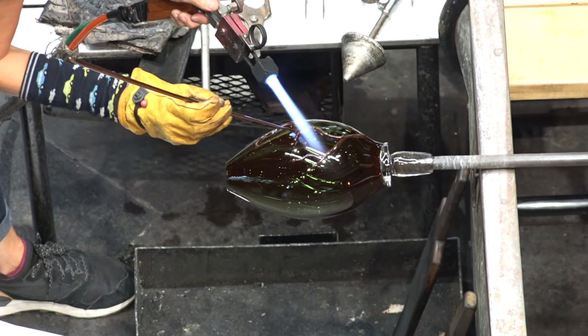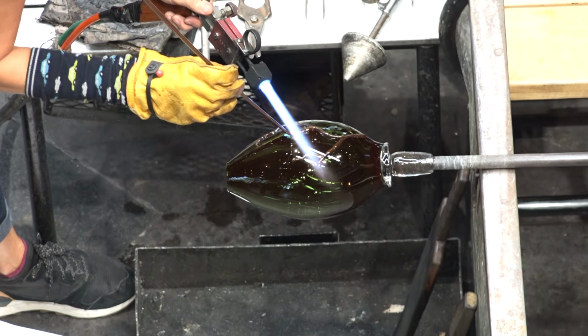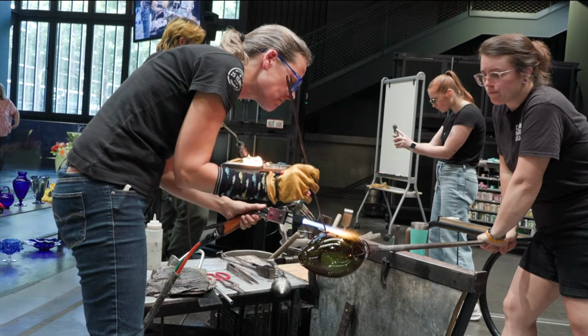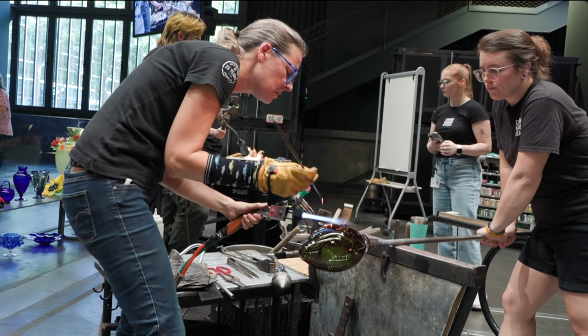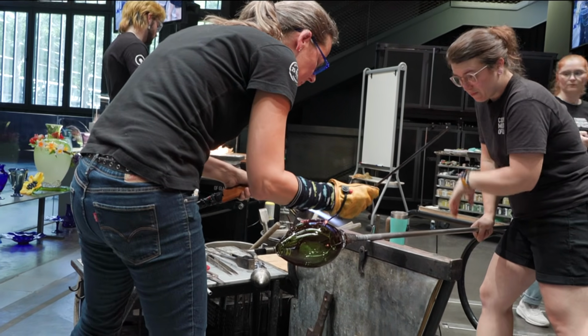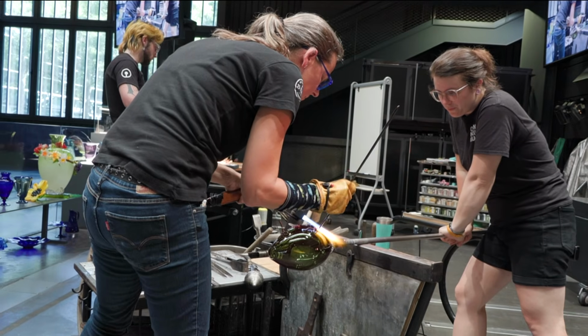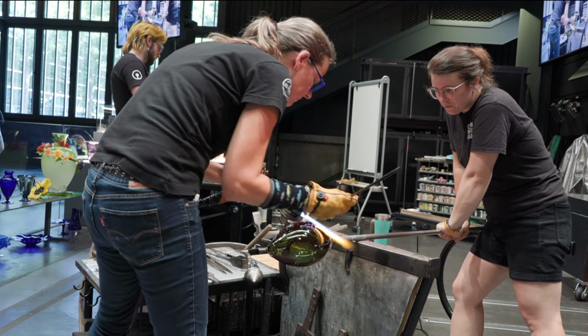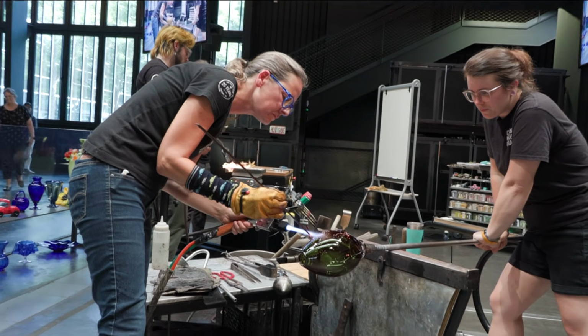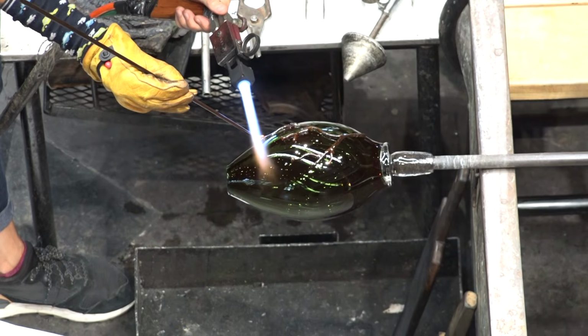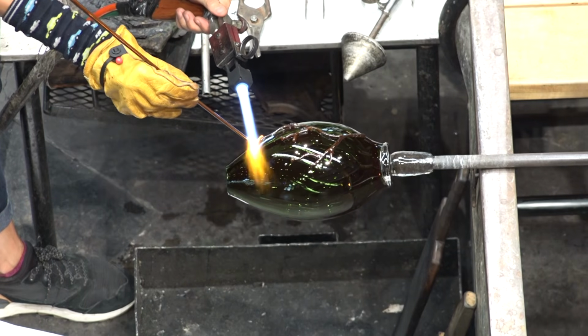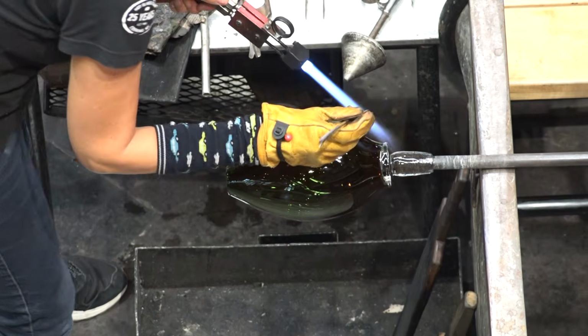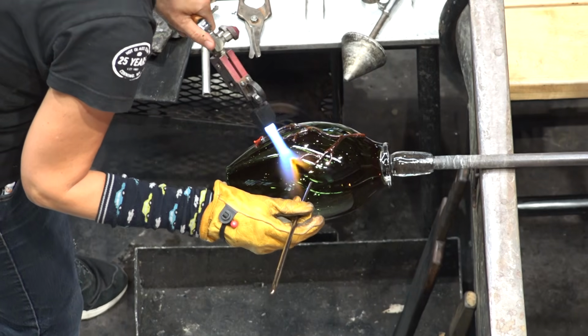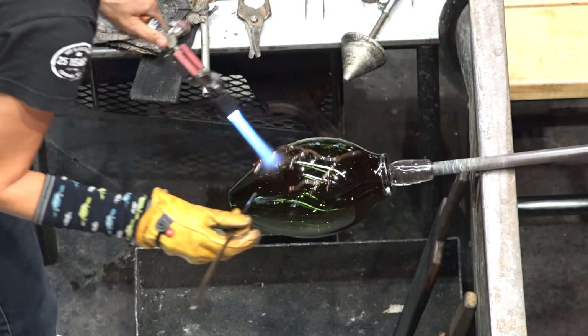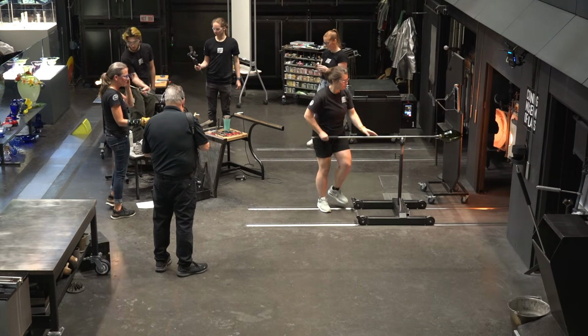So sometimes if you add a lot of a dark color, that color could be softer, heat up quicker and become softer. If you use some opaque oranges or white or red, sometimes those can be a little stiffer. And so sometimes working with multiple colors can be tricky because when you're inflating a bubble and you have softer areas and stiffer areas, that can be problematic. So yeah, we do have to plan for that when we're working with the colors.